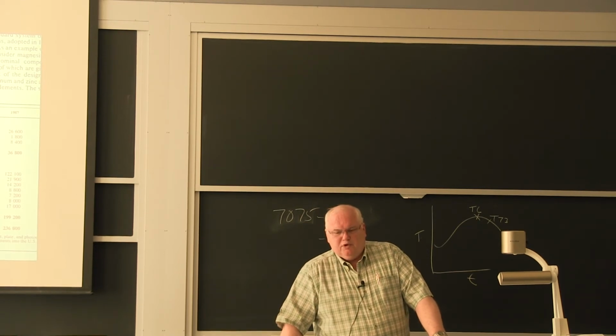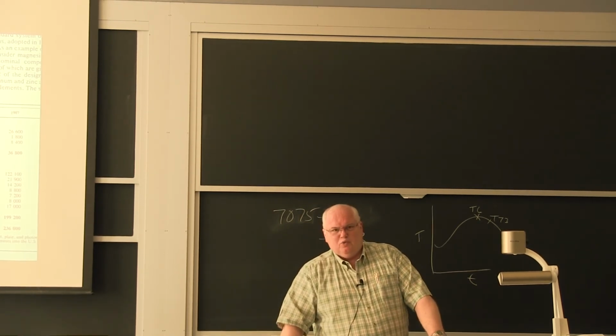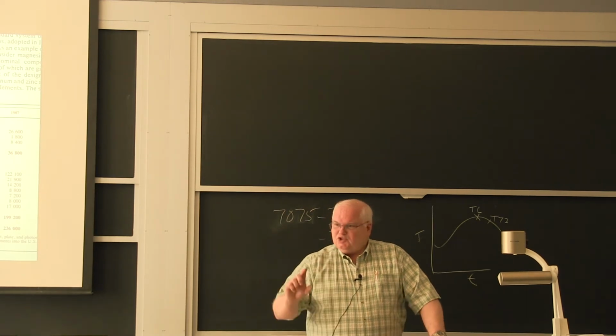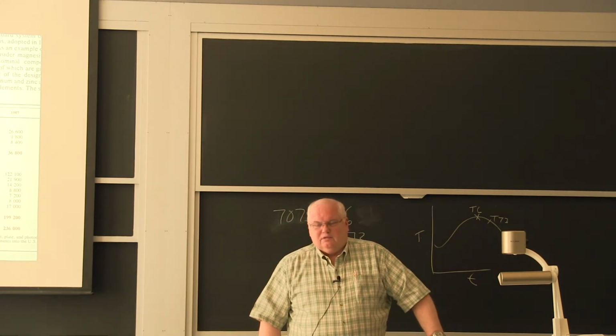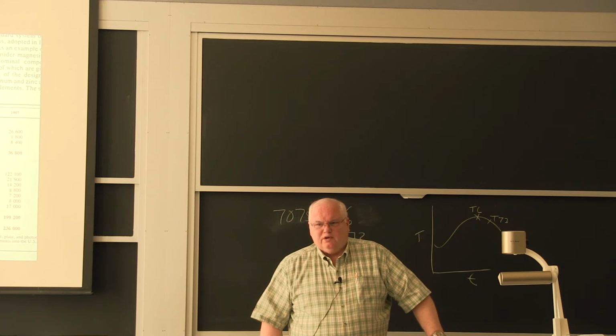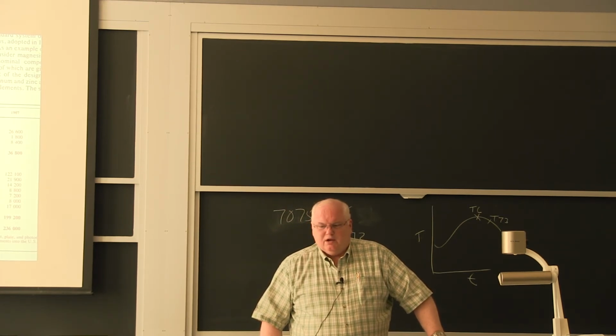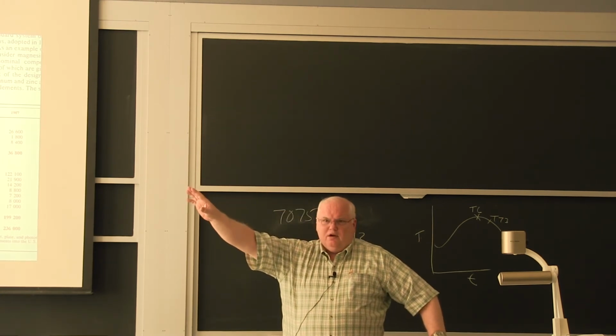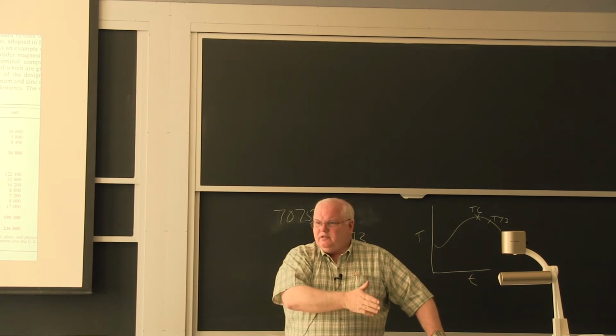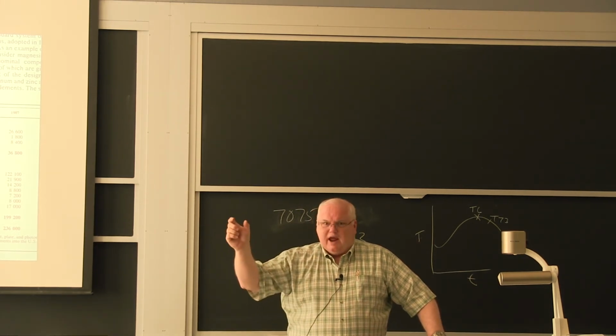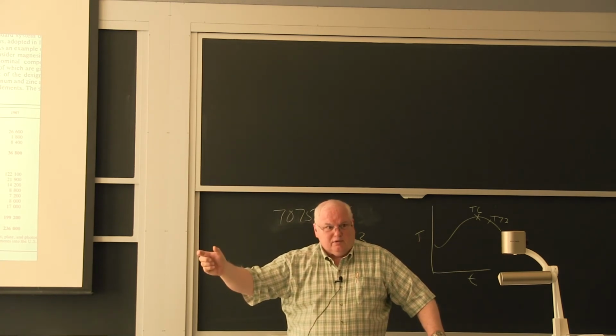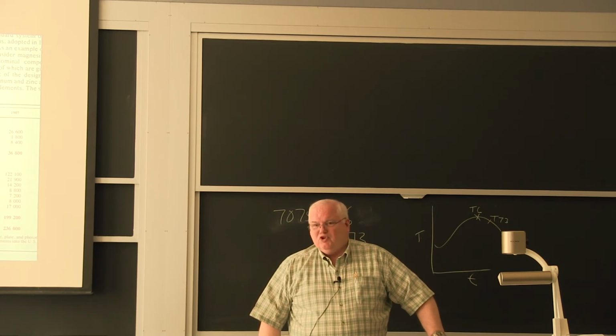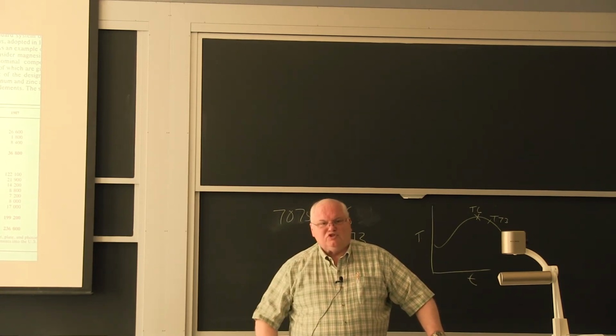Magnesium is better. The problem with aluminum, if you have certain ions in your water, the aluminum can form a passive scale on the surface. And all of a sudden the aluminum becomes non-anodic, becomes cathodic. Aluminum is sometimes called amphoteric, which means it can switch its polarity in the galvanic series. So aluminum in properly conditioned waters is fine as an anode material, but magnesium is better because if you look at the galvanic series, all the way over here, the most reactive is magnesium. And all the way over here, the least reactive is graphite. And it's like an extra half volt you get out of magnesium compared to zinc. I mean, magnesium is really the most electroactive of our common sacrificial anodes.